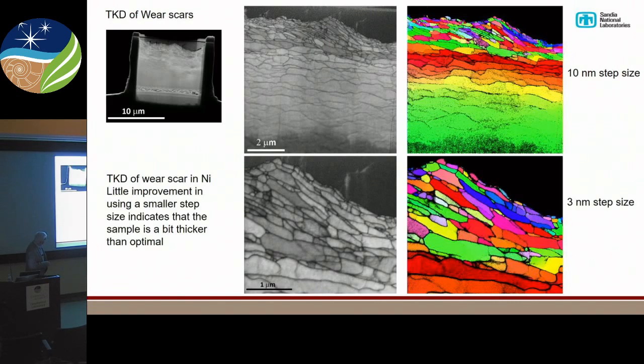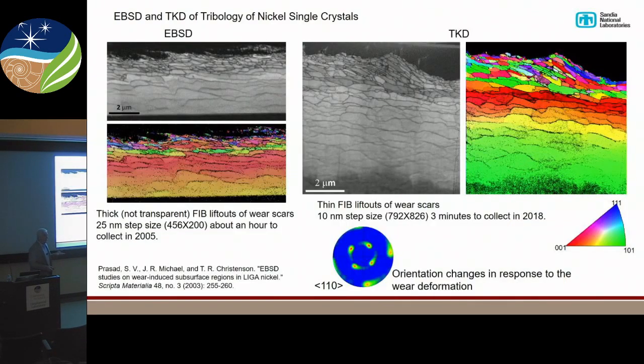Of course, the problem here is if you're trying to do 1 micron at a couple nanometer spacing, that's a lot of pixels. So these tended to take a long time. SEMs aren't set up well with stages for long-term drift problems. So we were starting to see the fact that drift was becoming very difficult to deal with. However, these new fast detectors now have fixed that for us, because a typical map now, the map I just showed you, this is at 10 nanometer steps, took about 3 minutes to collect, right? So we don't have to worry about drift so much anymore, long-term drift. Back when I was doing this for the first time, these were thicker samples, but this was taking an hour or so to collect even at 25 nanometer step sizes.